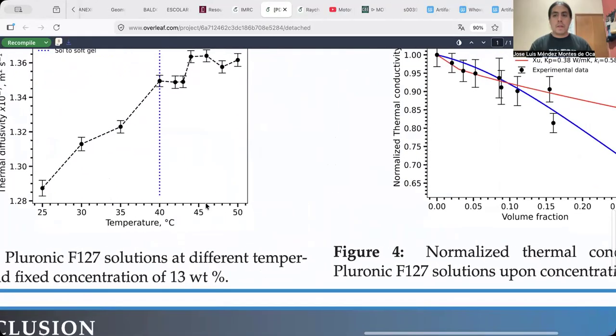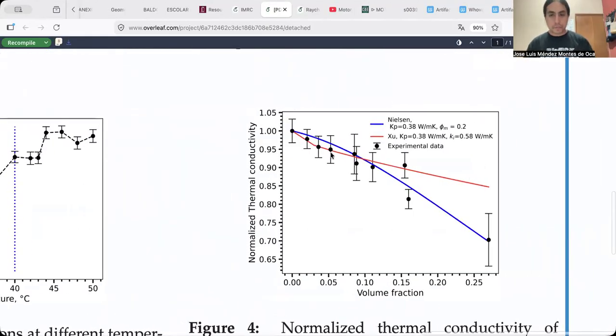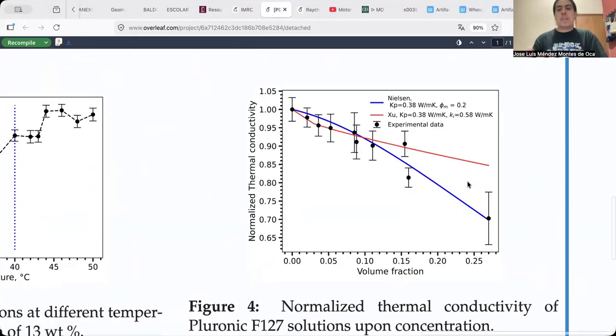Here we have the fit of our experimental data with the models. It can be observed that the Lewis-Nielsen model, this line in blue, fits better for higher concentrations but fails for lower concentrations, and the Xu model, the red line, fits well for low concentrations but fails for higher concentrations. We regard that this is due to the nature of the formulation of these models.